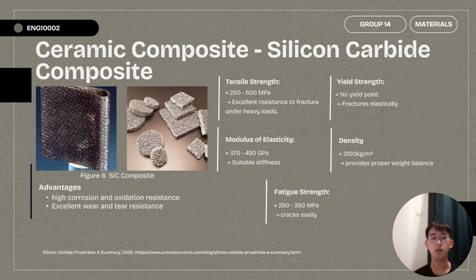Next, I will talk about the silicon carbide composites. The tensile strength of silicon carbide composites is around 250 to 500 megapascals. The high tensile strength of silicon carbide composites means it can offer excellent resistance to fracture under heavy loads. The modulus of elasticity of silicon carbide composites is around 370 to 490 gigapascals.